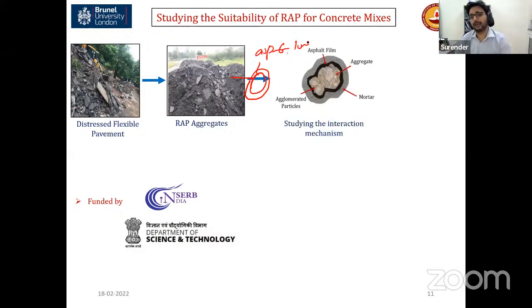So the issues with this, apart from the asphalt content, which is organic in nature, are agglomerated particles, because asphalt is a glue which will bind the aggregates together, and the binding capacity between these aggregates is very, very low. So when you use it in concrete, obviously the bonding affinity of the organic coating and the inorganic cement mortar paste is very, very less. And when we have a large amount of agglomerated particles, it further reduces the mechanical properties. So we are studying the interaction mechanism, what the various parameters of the asphalt coating, aggregates, or agglomerated particles are that affect the bonding potential, and how to improve it.